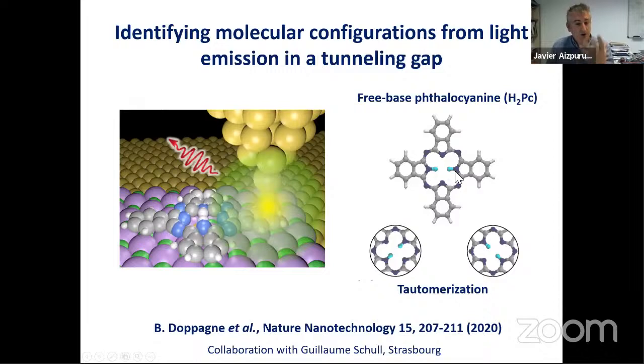So this phthalocyanine has these two hydrogens here. And this phthalocyanine is a very good emitter, but it shows two tautomers. In chemistry, these two tautomers are molecular objects with the same composition, but they have a different structural organization of some atoms. So same chemical composition, but different structural disposition of the atoms, right? If you have these hydrogen atoms like this or like this, you have the same molecule, but one, for example, will emit with the dipole in this direction and the other one will emit with the dipole in this direction. So actually, the group in Strasbourg, Guillaume, put this molecule in this plasmonic cavity, activated it with the current, and mapped the emission from this molecule in the plasmonic cavity, right?